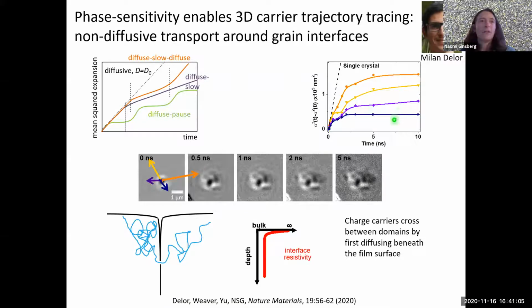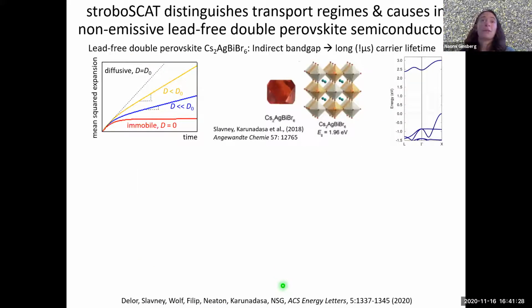Okay, so that's basically the way that we arrived at this idea of these charge carriers having to go deeper beneath the film and that there might be a resistivity profile at these interfaces that looks something like this. And this is actually something that could be really valuable in terms of thinking about how you make solar cells out of these materials. Okay, so one potential way to extend the migration length of these charge carriers further is to try and extend the carrier lifetime, for example, by manipulating the band structure. And that's something that Karunadasa's group did here by alternating the metal at the center of these octahedra, so that, in this case, with these metals, generates an indirect band gap as calculated, as it turns out, by Marina Filip when she was a postdoc in the Neaton group.